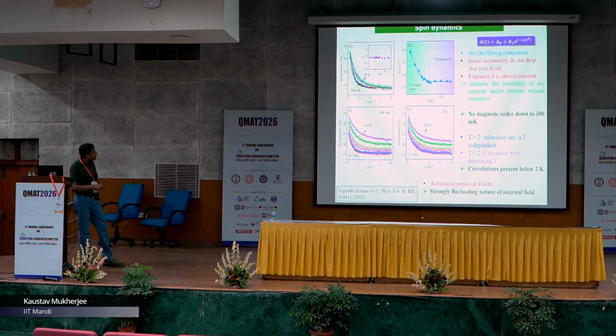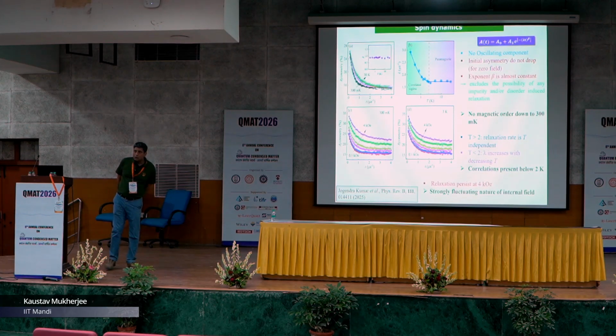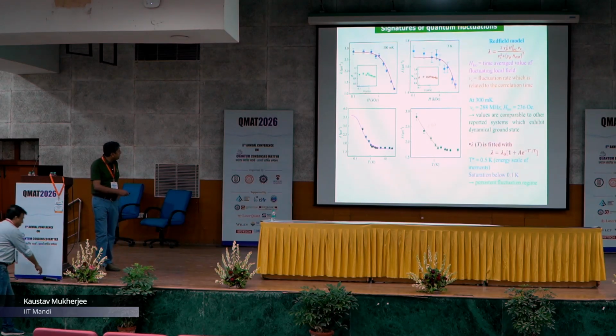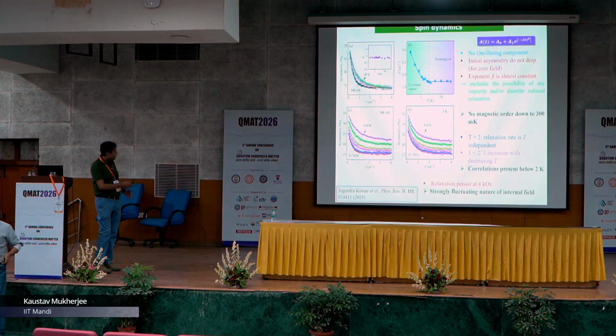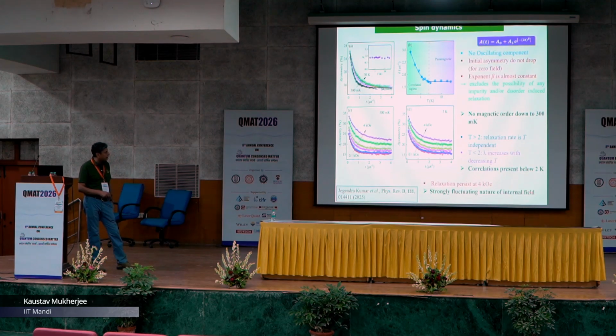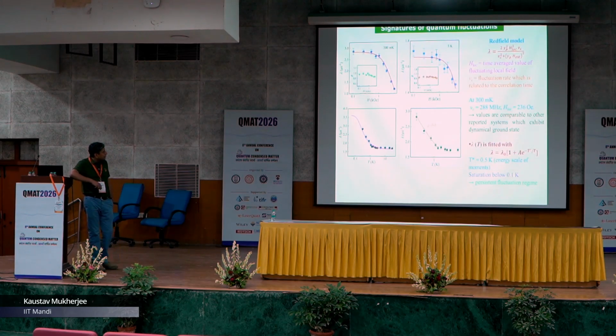Also, we found that the relaxation rate below 2 Kelvin increases with decreasing temperature, whereas above 2 Kelvin it is constant. So, it implies that correlations are present below 2 Kelvin. Now, we also superimposed a longitudinal field, and what we saw is that the relaxation persists. So, it implies a strongly fluctuating nature of the internal field.